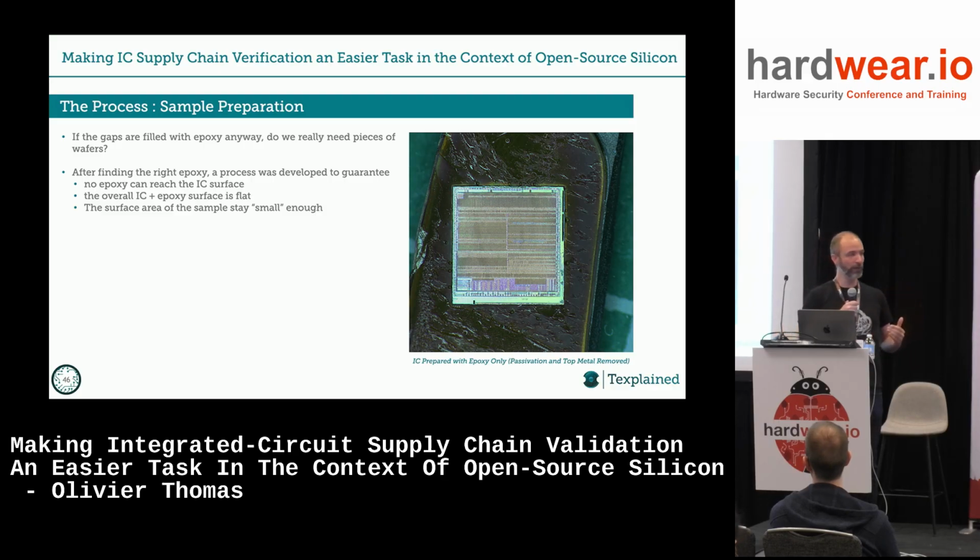And the fact that we used epoxy was also good because the plasma etcher that we have, at least, is not anisotropic. No, it is isotropic. So the side of the chip would be eaten first, and your chip will shrink in size. There's an easy trick to avoid this. You can put a marker pen and just color the side, it will protect the chip well enough, but this is better. On this picture, 2 layers have been removed. No side effect, it looks cool.